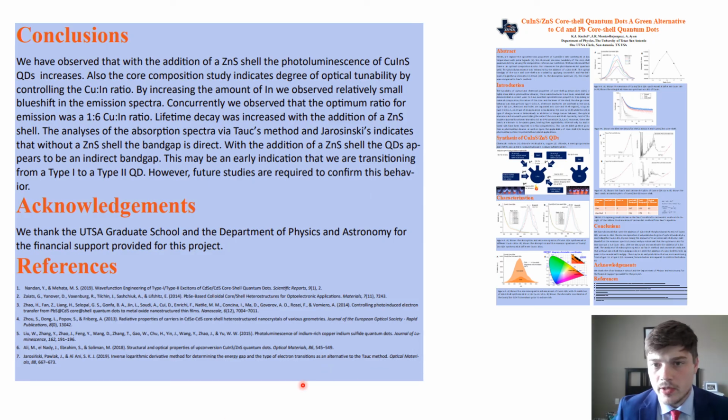To summarize our poster, we demonstrated that there is a degree of tunability by controlling the composition of your particles as related to the emission spectra. If you synthesize with the indium-rich synthesis, your particles will appear to be more blue. And if you synthesize with the indium-deficient or indium-poor synthesis, they will emit more in the red. However, this degree of tunability is relatively small, within a few nanometers. So in general, these particles will emit around 650 nanometers.